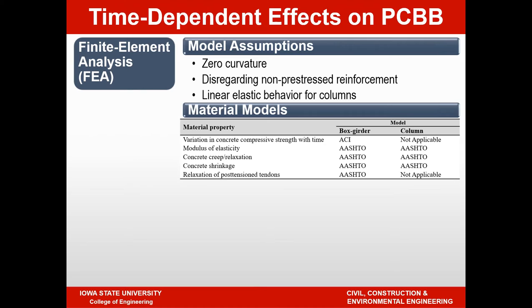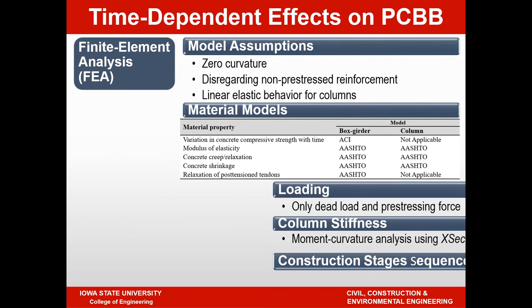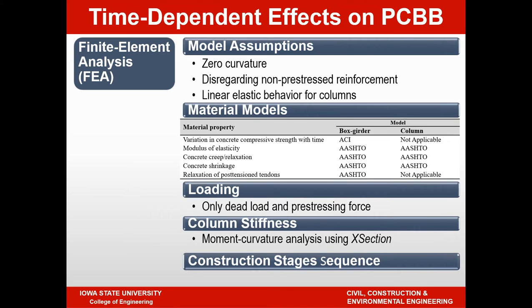The material models in the analysis were based on the concrete compressive strength with time, based on the ACI approach. The modulus of elasticity was assumed using the AASHTO recommendation, and the concrete creep, relaxation, and shrinkage functions were developed as recommended by AASHTO. We applied the dead load and prestressing forces. The moment curvature of the column sections was performed using a XSection, and the column stiffnesses were evaluated based on the moment curvature analysis, depending on whether it is a cracked column or uncracked column.